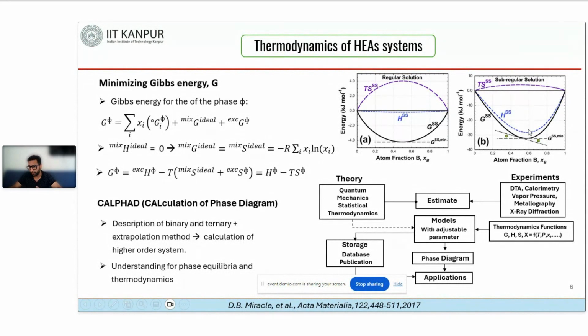So the enthalpy is not symmetric, so that leads to the Gibbs energy also not being symmetric about the equiatomic composition. Why I'm emphasizing that it is not symmetric about the equiatomic composition is because earlier it was thought that the equiatomic composition would have high configurational entropy, and that it would lead to high stability of this equiatomic phase. But we know with the subregular solution model that even a non-equiatomic composition can have a lower Gibbs free energy compared to the equiatomic composition, so they can have a better thermal stability.